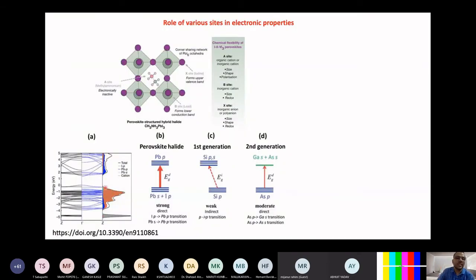So this is what I was telling, that you have this different role of various sites in electronic properties. So this is a perovskite. You have lead p orbital which makes the conduction band minima, whereas your valence band is made using the lead s orbital and halide p orbital. If you basically replace your iodine with bromine or chlorine, then your valence band gets shifted, and hence you find that your band gap is being changed due to the change in the position of the valence band maxima.